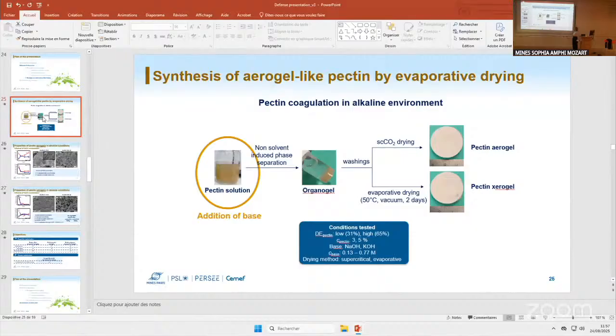But for sure, the gel is the most important part if we can control the gel. And for the structure of the network, we could potentially make the same structure. If we confirm that the combination of lower capillary pressure and higher mechanical strength of the structure is what let us perform evaporative drying, then we could potentially find cross-linking methods that give the exact same structure, avoiding deesterification, depolymerization, of course. So yes, gel is very important, I agree.